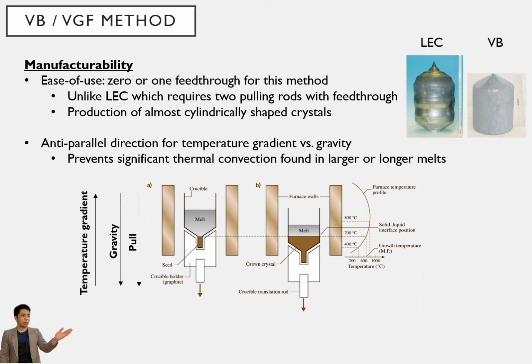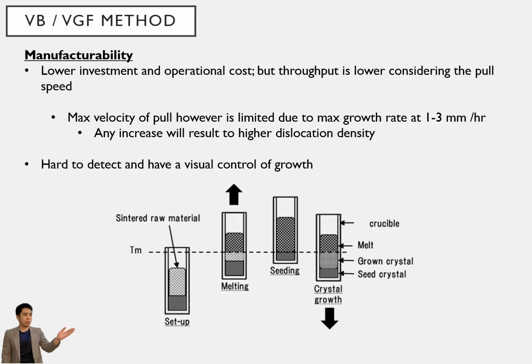The end product is also reliably consistent in a cylindrical shape, which you can see in the images on the right, which shows better product uniformity than LEC. The reason behind this is that the temperature gradient is antiparallel to the pull of gravity and its movement. This results in less thermal convection that may affect the crystallization temperatures experienced at various parts of the ingot found in long melts. This makes VB and VGF methods less costly in terms of investment and operating expenses for large-scale manufacturing.